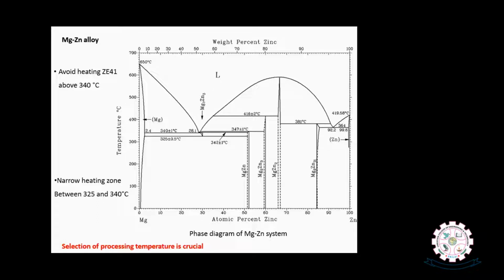Here we have, even though pure magnesium melting point is 650 degrees centigrade, because of the presence of 4% of zinc in ZK40 magnesium alloy, it is not suggested to go beyond 340 degrees centigrade. That means our metal forming temperatures must be less than 340 degrees centigrade. So compared with the AZ91 magnesium alloy, ZK40 magnesium alloy has even lower band of temperature ranges to deform the magnesium.